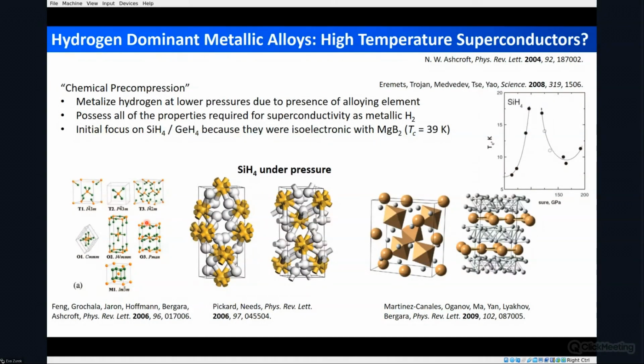And the initial focus, first of all, theoretically, there was a lot of theoretical calculations done, was on systems like silane and germane, because silane is isoelectronic with MgB2, and we know that MgB2 has a high TC of 39 Kelvin as a conventional superconductor at 1 atmosphere. And there were also experimental attempts to metallize SiH4, though the interpretation of these experiments has been questioned as to whether it is really SiH4 or some other compound that is giving rise to the superconductivity.